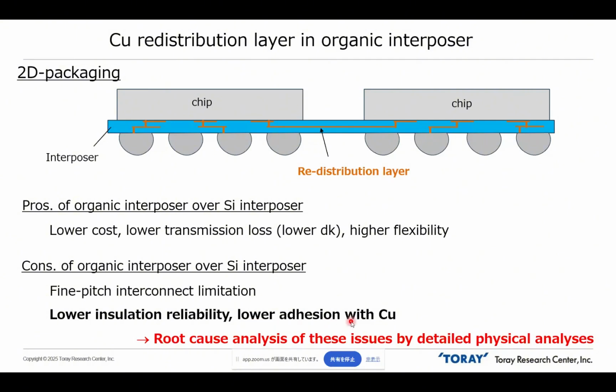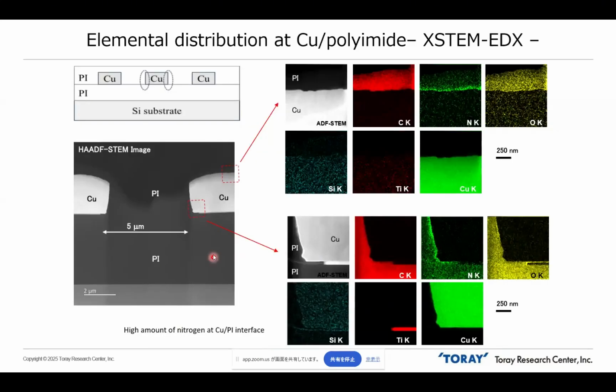Now we try to find the root cause of this issue by using our detailed physical analysis technique. This is a test sample of this case. In this case, the redistribution layer metallic interconnect is copper, and the dielectric is polyimide. The copper interconnect width and pitch is 5 micrometers in this sample. This sample has an adhesion problem between copper and polyimide. But this sample already has a patterned structure, so it is difficult to use macroscopic analytical techniques. So we try to find the cause of the poor adhesion problem by using high-resolution analytical techniques.